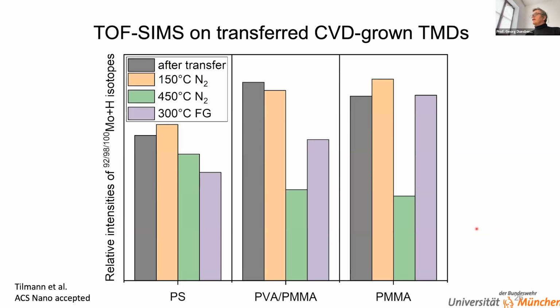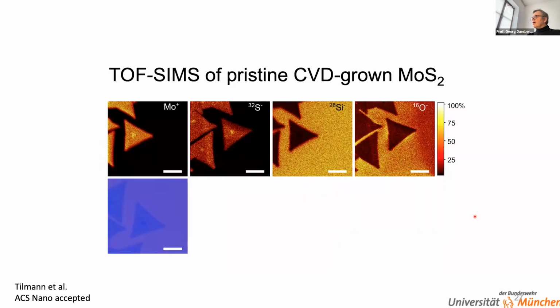And then we looked at the various annealing processes, for example, how effective they are for the different polymers. Annealing is often used for all TMD materials to clean them up. And we could show that some annealing procedures worked quite okay. For example, here for PMMA, a 450 degree anneal in nitrogen worked quite nicely. However, not so much 150 degrees. And for polystyrene, a 300 degree anneal in forming gas, a mixture of hydrogen and nitrogen, worked okay, but we also could show that we never completely got rid of these polymers. So what do you now think is new? Everybody in the community more or less knows that you have some polymeric residues if you transfer the materials.